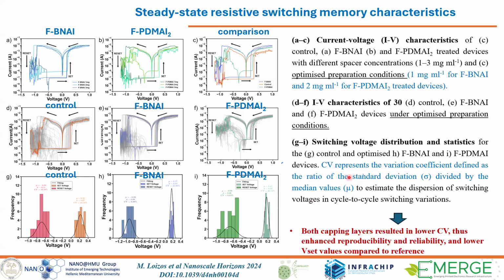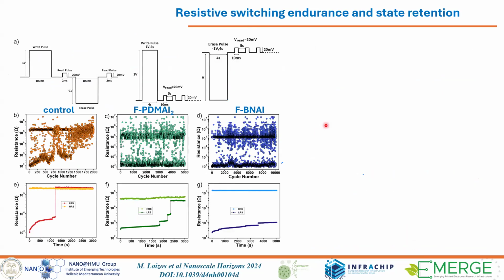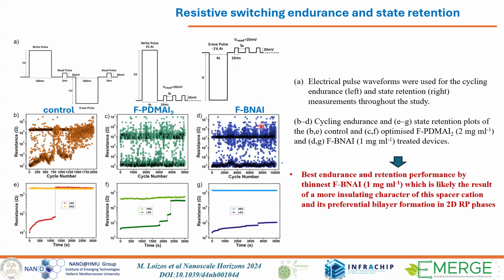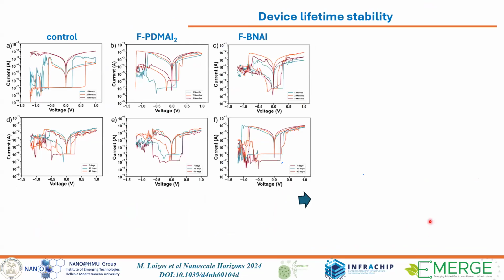And we identify that devices with the capping layers have both lower CV parameters, so lower variability. So we improve the reproducibility of our devices, and also the set voltage for the targeted materials are lower compared to reference. So this was one improvement. Then we also monitor the endurance and the state retention, control, and then type A and type B. Type B, so F-BNAI, was found the best, the most stable. We demonstrated more than 5,000 endurance cycles with very small degradation compared to reference, so it is much more stable.